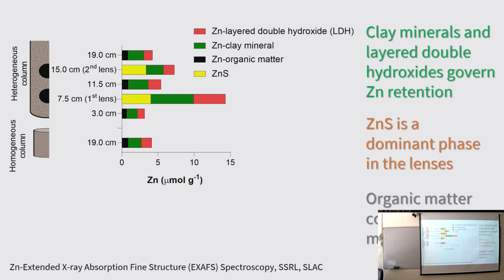However, zinc organic matter interactions were detected only in the sand, and a dominant zinc sulfide phase was present only within the lenses, likely due to a constant input of sulfate. So we have sulfate being reduced to sulfide, and therefore continuous accumulation of a zinc sulfide phase.